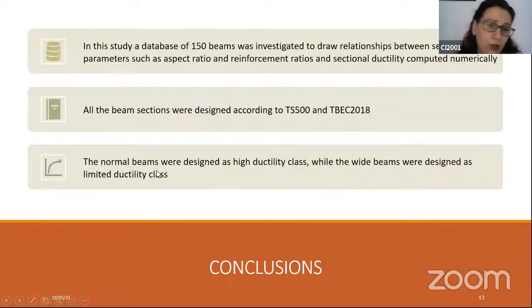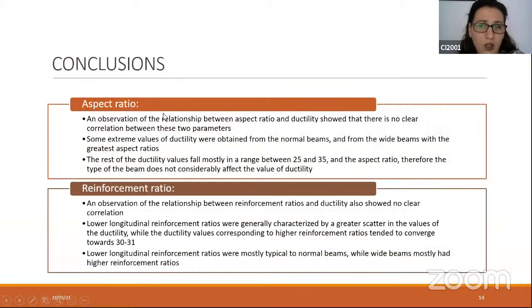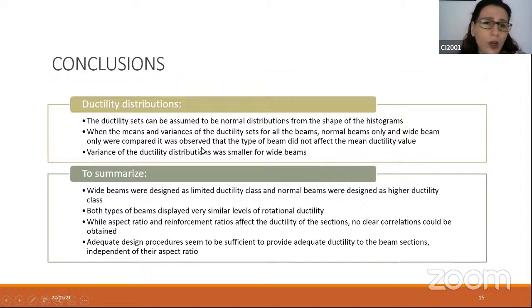So if we come to wrap up the study that we did, we had a database of more than 150 beams, which was investigated to draw relationships between, if possible, section parameters and ductility that was obtained numerically. And all the beams were code-designed. Normal beams were high ductility and wide beams were limited ductility. But we were not able to find a clear correlation between the ductility and the aspect ratio and ductility and reinforcement ratios. We observed that there was a ductility range between 25 and 35 mostly. So we thought that ductility could be more treated like a distribution, and this was also supported by the fact that the mean values of ductility were very similar for wide beams and normal beams.